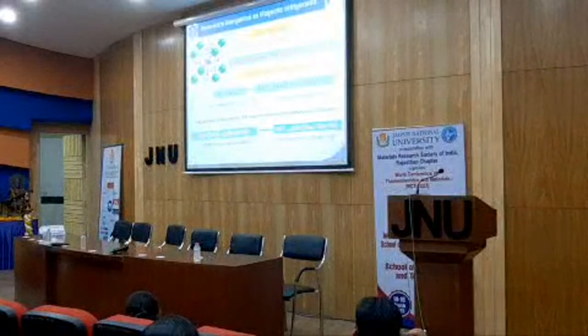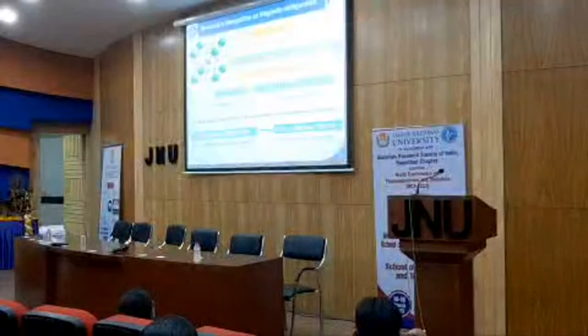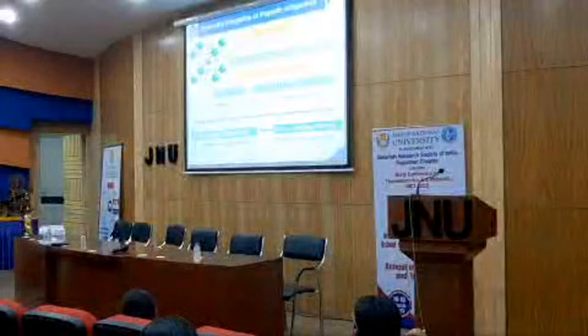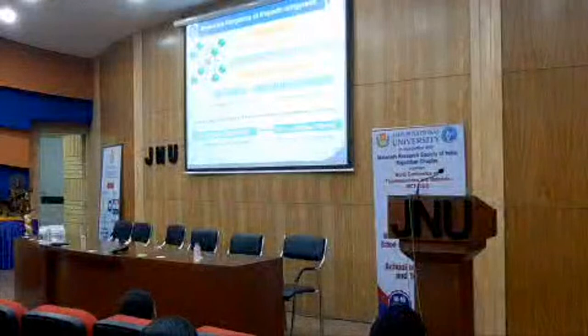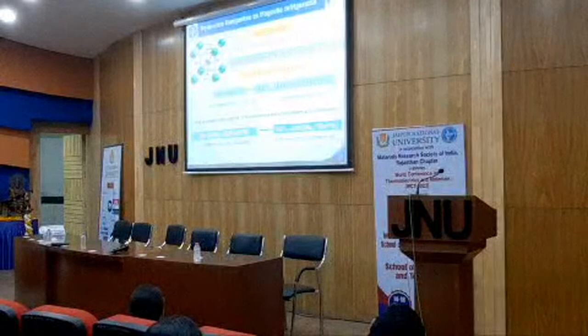Now, when we dope with some alkaline elements, because the requirement is there, doping, I will tell in the next slide. When you dope these alkaline materials, what is the oxidation state? It is a 2+ state. So when partial replacement happens at this rare earth site, which I mentioned is 3+, with partial alkaline elements, there is some charge neutrality. Because of the presence of 2+, the manganese site splits into mixed valency in order to compensate the charge neutrality. So whatever the percentage of the rare earth alkaline material you put, the corresponding Mn 4+ state converts. So that 4+ state creates a mixed valence. That is why these materials are popularly known as mixed valent manganites.